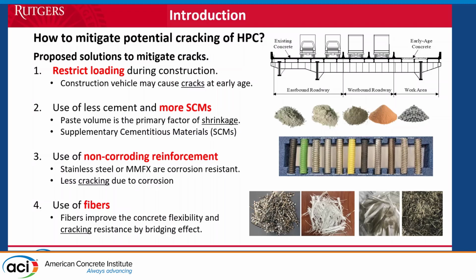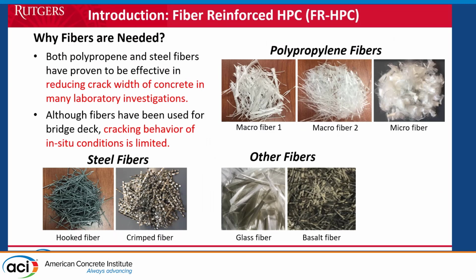For example, in the negative moment region, you will end up having cracking, and even in AASHTO, the design is silent about that. So we tried to figure out a way to control the shrinkage, but at the same time try to use stronger fibers to intercept any cracking and keep the cracks at a small size.